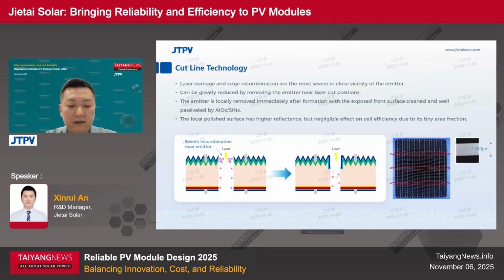During cell fabrication, the emitter can be locally etched away right after its formation, and the exposed surface will be clean and well passivated by aluminum oxide and silicon nitride, just like the rest of the front surface. Higher reflectance at those spots only causes a very negligible effect on cell efficiency due to the very tiny area fraction. For our standard process, the lines are only 300 micron wide, and for one cell, there will be only 2 or 3 lines. But they can be made wider if the clients need larger tolerance for laser cutting.